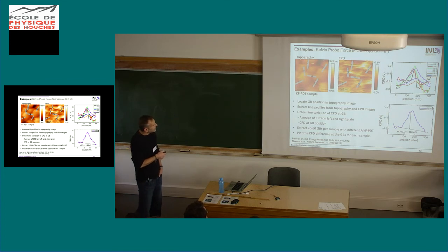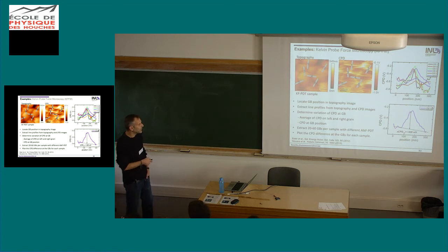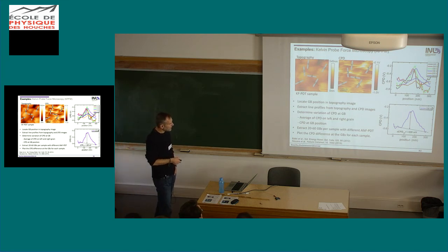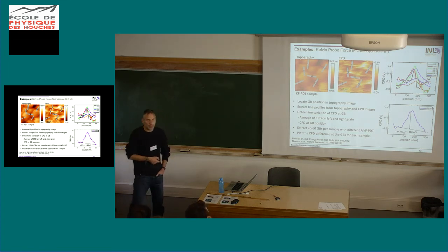So normally what we do here, in order to not get confused by this image, is we look only at this one and we identify our grain boundaries. We decide which ones we want to analyze. And then we take this line profile across the grain boundary in our contact potential difference. So we get a bunch of these line profiles here, and we do this in macroscopically different spots on the surface. And we analyze this by looking at the value on the grains, and then we take the difference to the value at the grain boundary. So this grain boundary here would have a positive change of the contact potential difference of 320 millivolts.